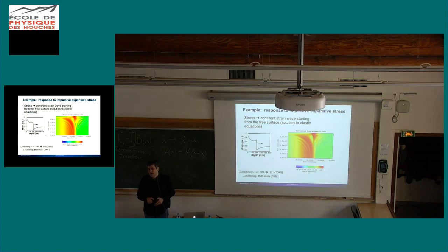So you would need a system that demagnetizes on a similar time scale, or at least faster than these phonon periods, and has a larger transfer of angular momentum, which was not within the repertoire of what we were able to grow. You can have a larger magnetic moment, but then it's harder to get a smaller demagnetization step. So in terms of swapping materials, I don't see a huge amount of hope of a larger effect. What we're mostly interested in is designing samples with more structure, to look at multiple interfaces and have them constructively interfere. We could look at higher wave vectors with a multilayer sample and get higher sensitivity at higher Q vectors that way.